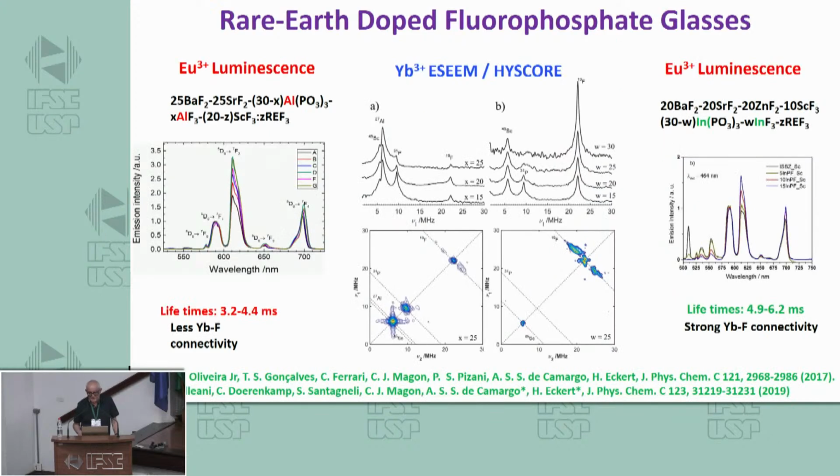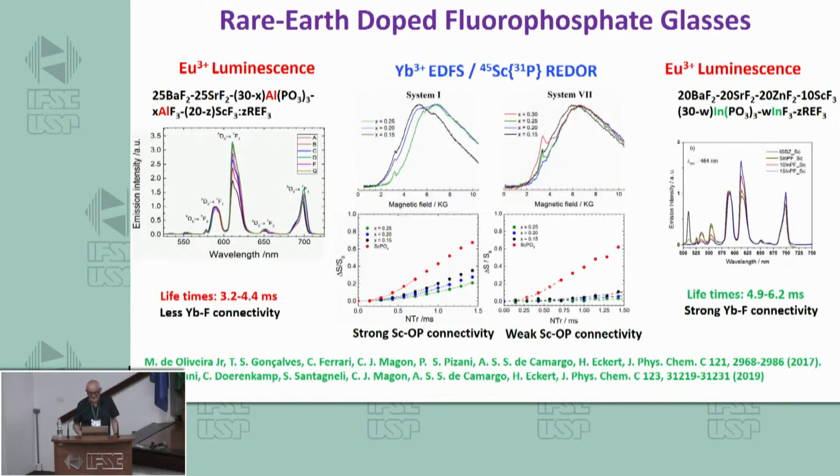Yeah, and then we have analyzed this and basically found that the ligand distribution between phosphate and fluoride depends very much on the system that you study, but certainly what one desires is generally that the environment of the rare earth is dominated by fluoride, and we were able to find a suitable system on this, and the references are shown over here.